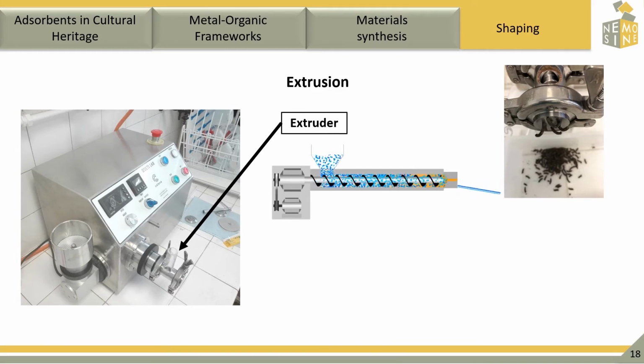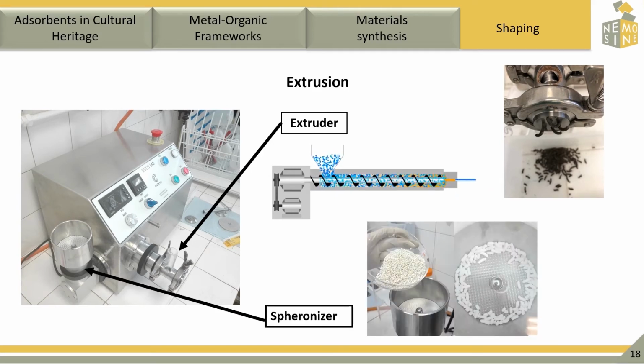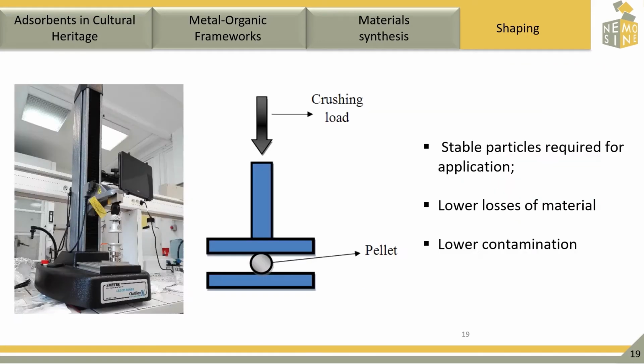In addition, we spheronize our extrudates in order to obtain more condensed particles that are even more stable and that have a uniform size distribution. So finally, to confirm if our particles are stable, we do a compressive test where we measure the breaking point. A sphere is put in the middle of two platforms and then it is crushed. So we change the force with time and we see the point of crushing of this shaped material.